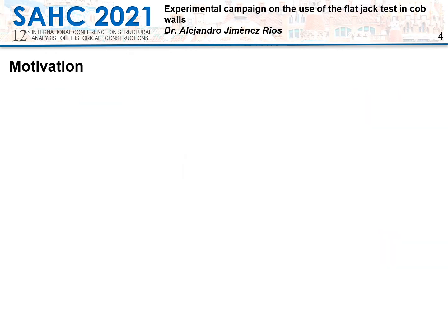The flatjack test is one of the most applied investigation techniques in the field of cultural heritage conservation. The purpose of this experimental campaign was to assess the feasibility of the technique to measure the average compressive stress levels in existing cob walls and determine their mechanical properties.